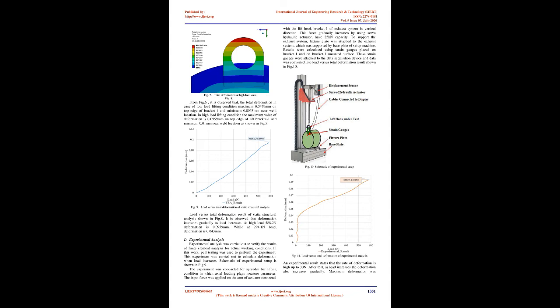The analysis results of total deformation at low load case is shown in Fig.6. From Fig.6, it is observed that the total deformation in case of low load lifting condition is maximum 0.0479 mm on top edge of bracket 1 and minimum 0.0053 mm near weld location. In high load lifting condition the maximum value of deformation is 0.0959 mm on top edge of lift bracket 1 and minimum 0.01 mm near weld location as shown in Fig.7.